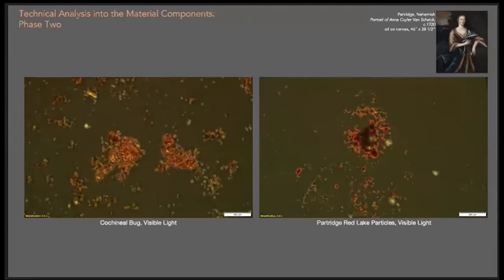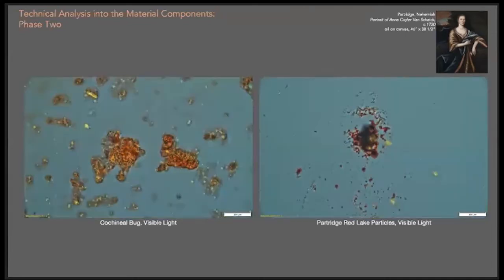In addition to cross-section analysis, we perform polarized light microscopy on loose pigment samples, which allows us to examine the pigments under the microscope and compare them to known samples. On the left is ground cochineal that's used to make red lake, and on the right is a sample from the portrait of Anna Cuyler Van Schaick. We examine the particles in normal light, shown here, and in cross-polar, seen here, where the light used to examine the particles is focused solely on the particles themselves.